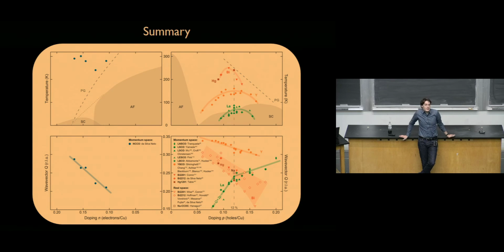Well, if you can pattern it at a nanoscale, maybe, yes. I mean, correlation length is of the order of, in the best case scenario, 100 angstrom, so 10 nanometers in the best case scenario.